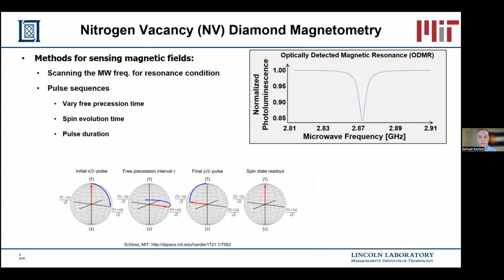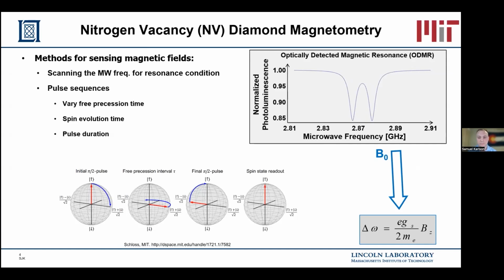The nitrogen vacancy center becomes a magnetic sensor when a resonant microwave field is applied to the system, which transfers population to the MS=1 state. Since more population is in the MS=1 state, fewer optical photons are emitted as they return to the ground state through the non-radiative decay pathway. A static magnetic field causes a Zeeman interaction that splits the degenerate ±1 states and increases magnetic sensitivity.